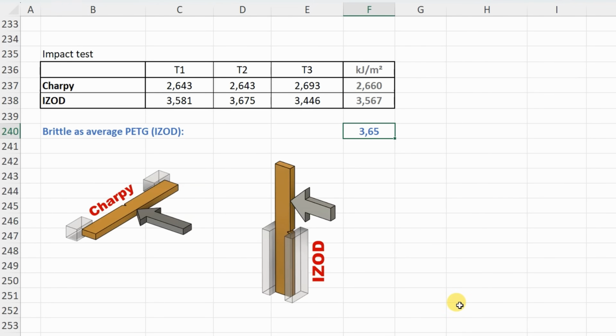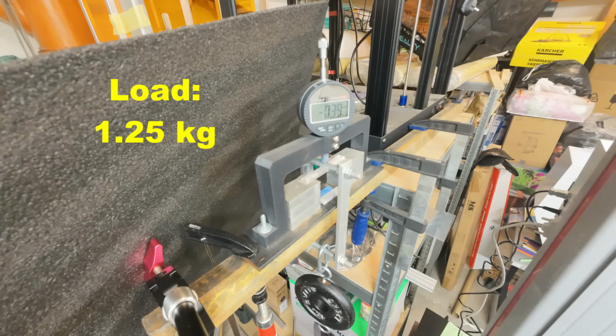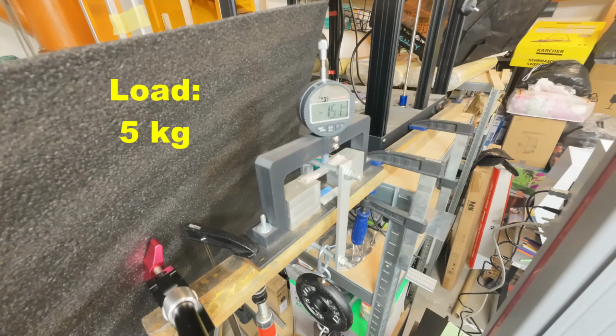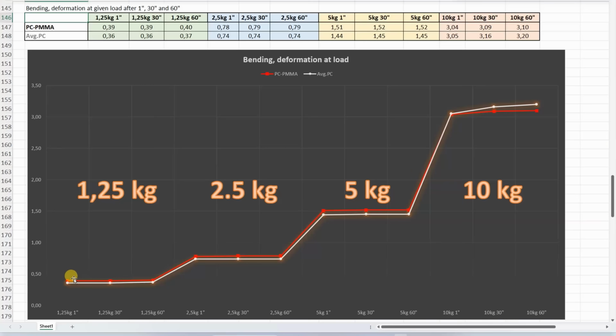PETG, for example. 3-point bending test, distance between supports is 50 mm, and I'm placing these loads one by one and measuring the deformation after 1, 30 and 60 seconds. Currently this is the deformation under 5 kg and under 10 kg. Now let's analyze the data. Very similar deformation at the beginning, a little bit smaller on the average polycarbonate, but look at this, under 10 kg, this Durabio handled better this bigger load compared to the average polycarbonate. Less additional deformation during that 1 minute.